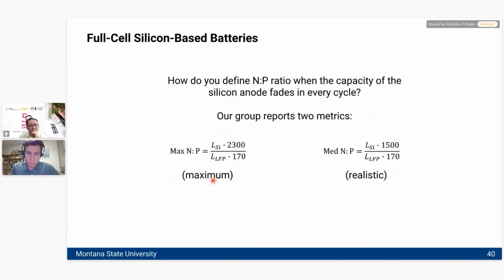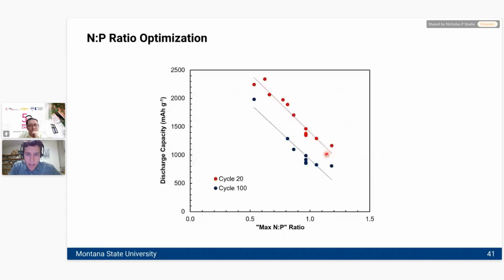And so, what we do in our group is we have to define metrics based on theoretical capacities of silicon versus whatever counter electrode we're using. In some cases, we define our NP ratio based on a very optimistic capacity of silicon, 2300 milliamp hours per gram. Sometimes we use a much more realistic value of about 1500 milliamp hours per gram. This gives us numbers that are in the realm of what ends up actually happening in the cell. So you can use either one. It doesn't really matter which metric you use, as long as you explain how you're defining it.